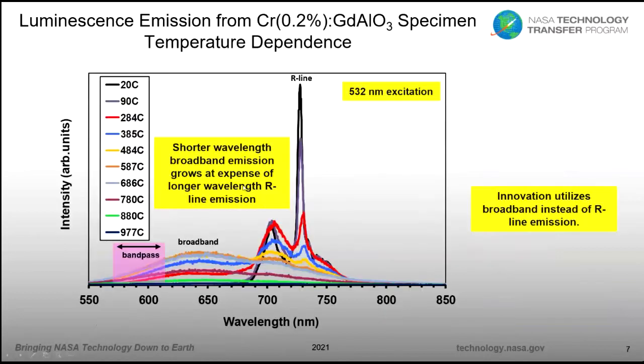Okay, that's some of the physics. Let's go on to some of the data. This shows how the emission spectra change with temperature. At room temperature, in this case around 20 C, you only get that R-line emission that's been used by many others. It's pretty sharp, around 730 nanometers for chrome-doped gadolinium aluminate. Plus, it has a vibrational sideband.